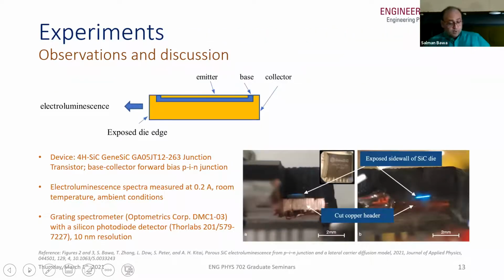So what we did was to use a 4H silicon carbide, and 4H is a very common polytype of silicon carbide, and this was made available by GeneSiC. We used the junction transistor that you see in the figure on the top of the screen, and we forward biased the base collector junctions and took the electroluminescence spectra at about 0.2 amperes in room temperature and ambient conditions, using a grating spectrometer with a silicon photodiode detector.